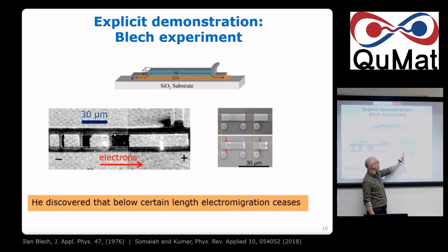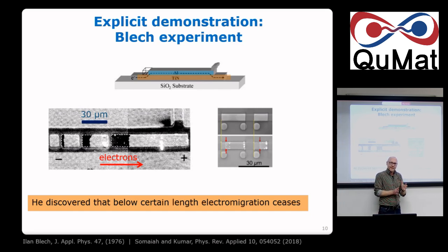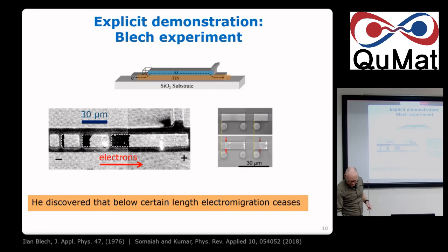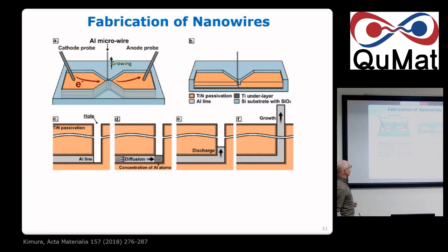What happens is that you build up a gradient of concentration. It becomes very dense on one side and very porous on the other side. And that actually makes a gradient in the opposite direction. So at a certain moment, when it's too short, it doesn't work anymore. Okay, but I'll show you an example of someone who used this to make nanowires.